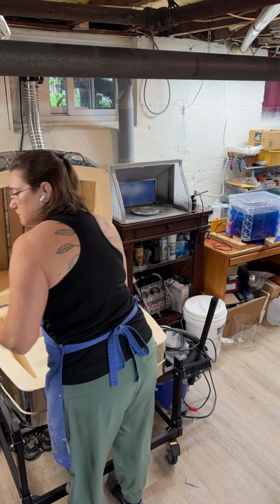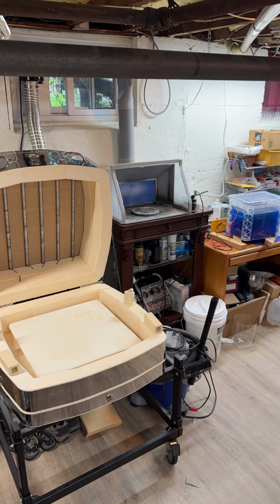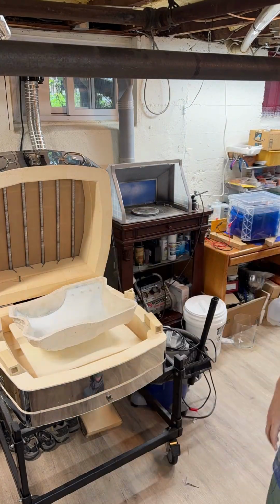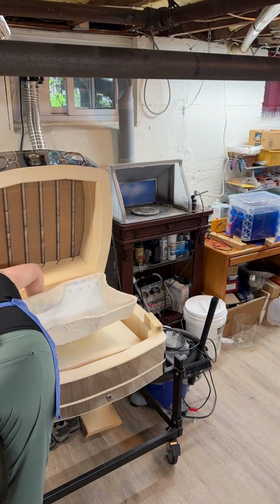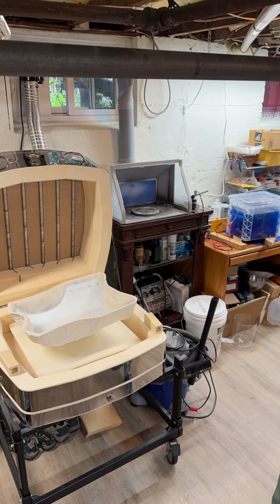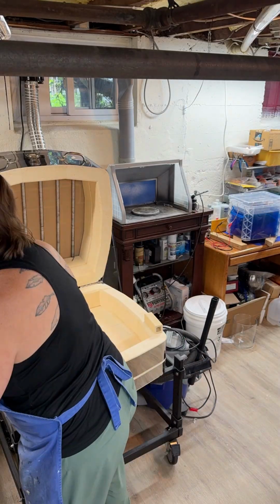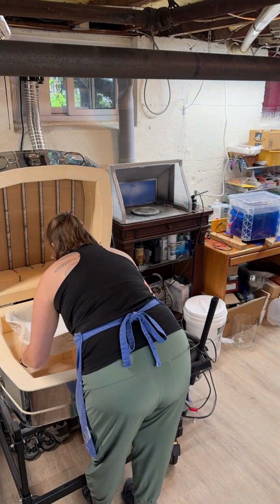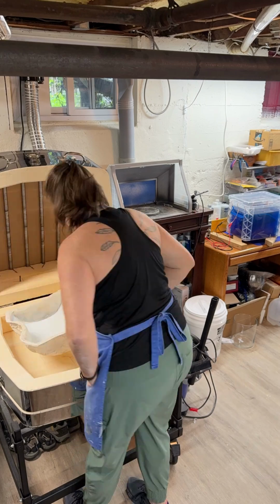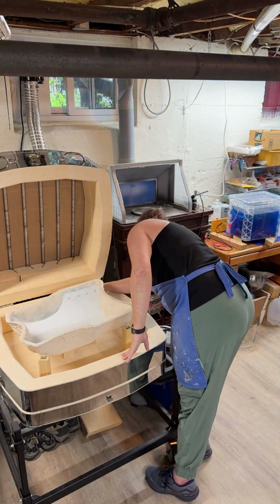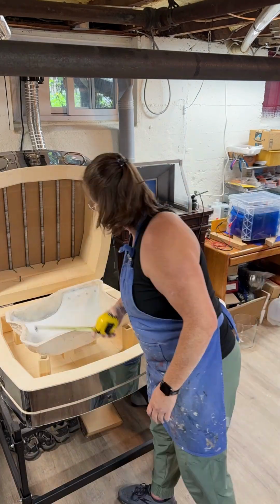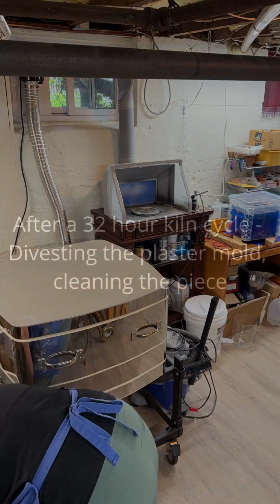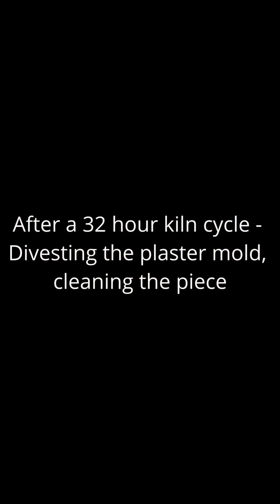The piece will do most of its drying in the kiln, so I can load it into my Skutt Studio Pro while it's still a little bit damp. It only just barely fit. I use ceramic kiln stands to keep it off the shelf so no damage is done and so that air can circulate. After a 32-hour kiln cycle of slow drying, melting, and annealing, it takes the piece several more hours to come back to room temperature before it can be safely removed.